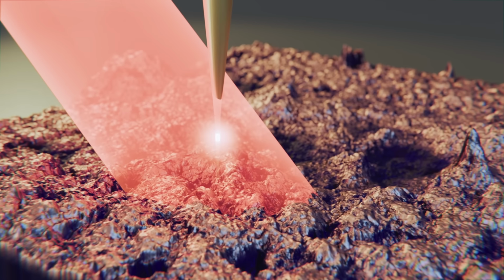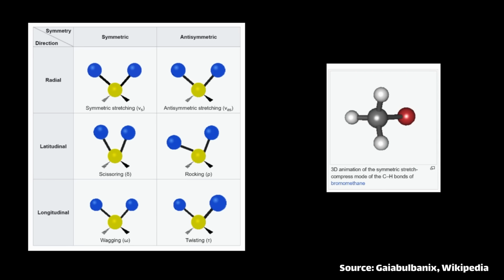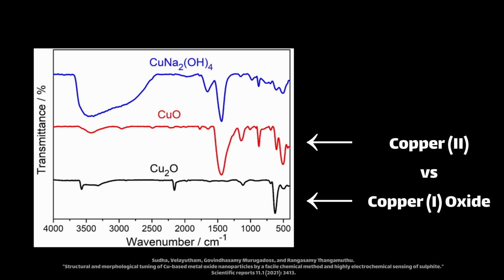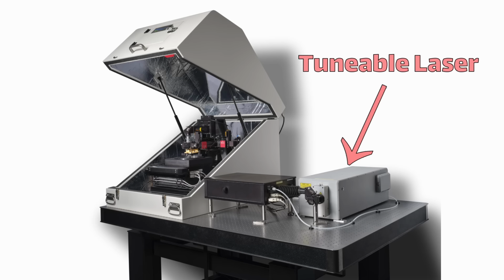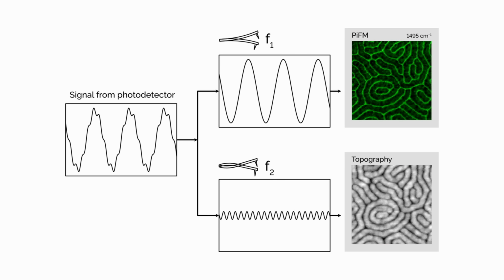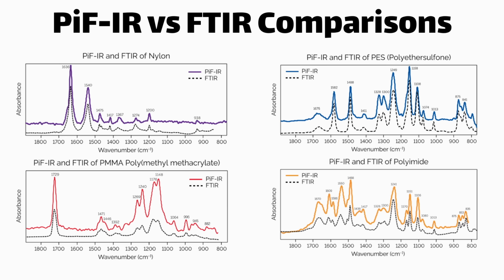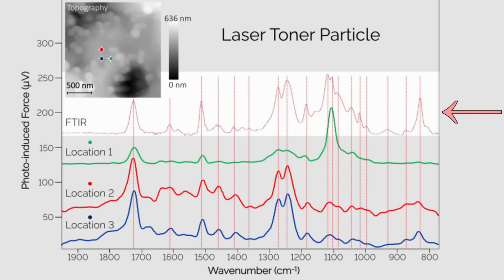Importantly, this interaction is mediated by the same mechanism that's used in IR spectroscopy, namely that different molecules absorb and resonate at different IR frequencies. So the Vista 200 works by scanning a tunable infrared laser across a wide range of frequencies, and then measuring the resulting photo-induced forces on the tip. The forces at different frequencies are then plotted to generate a traditional IR spectra. You get a chemical makeup like IR, but resolution like an AFM. And because it basically is an atomic force microscope, you also collect topographic data at the same time.